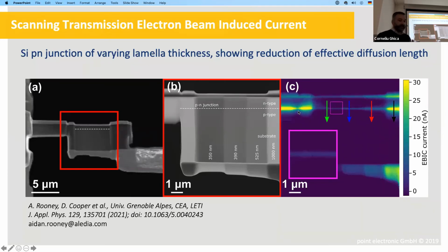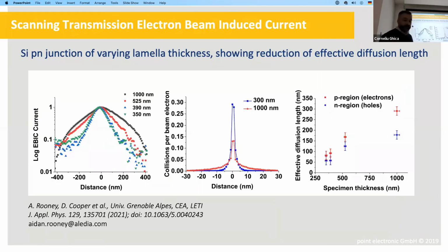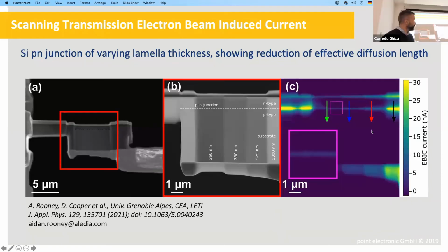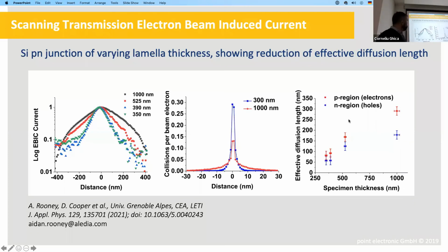And you see that the thinner the lamella, the smaller the signal, because we have less material to lose energy and therefore less induced current. As we have thicker materials, more current and also more diffusion. Is it more diffusion because it's thicker, or are there some other things at play? We can extract line profiles going across these EBIC signal images, and using the standard EBIC analysis, we can extract the diffusion length of minority carriers.